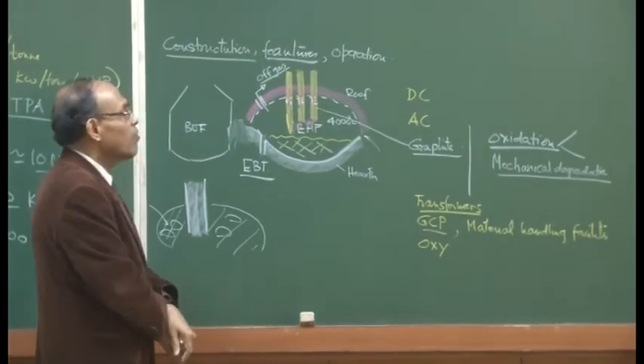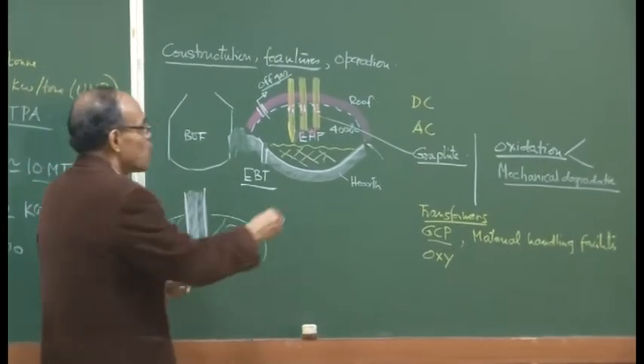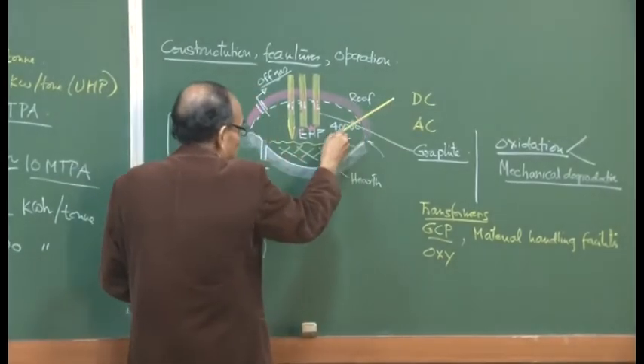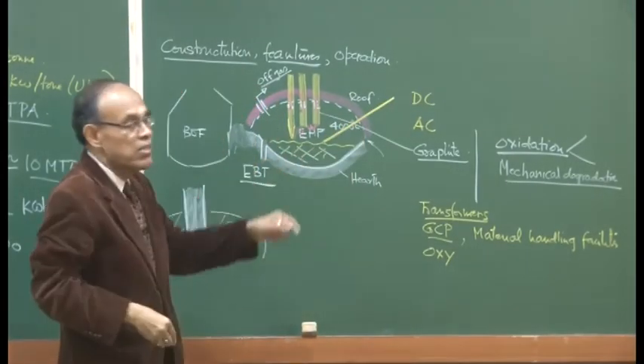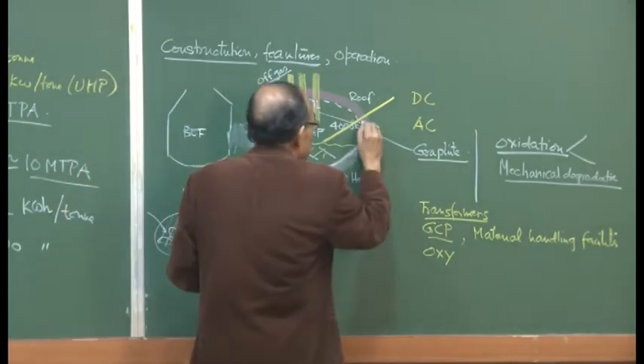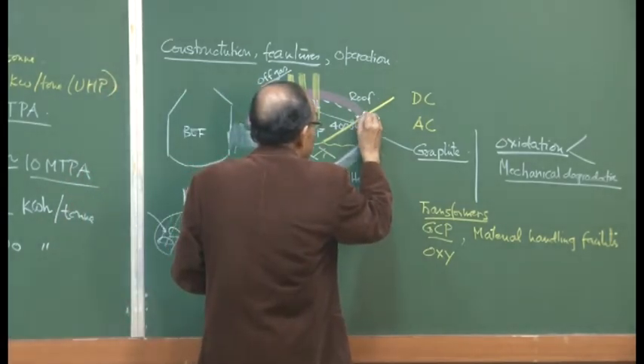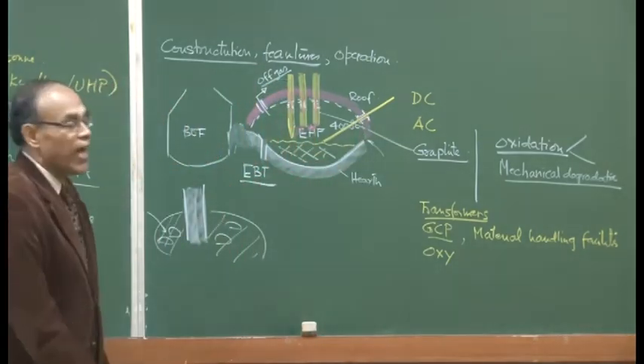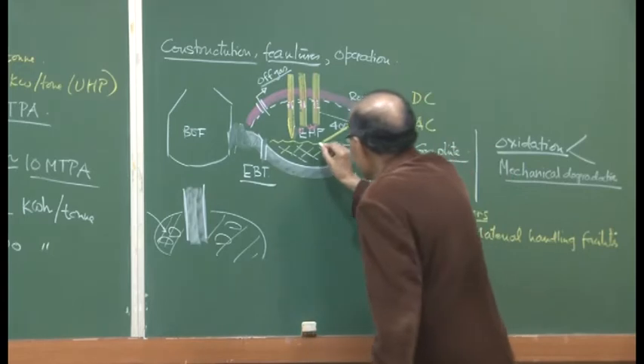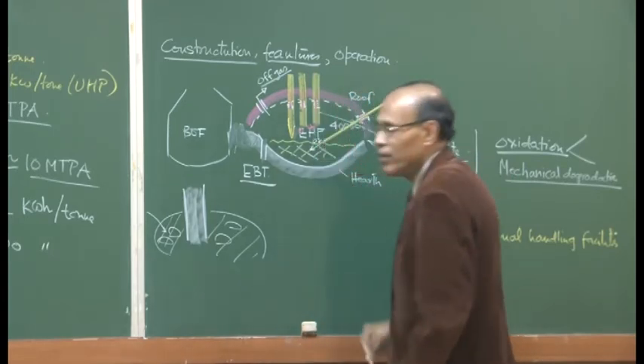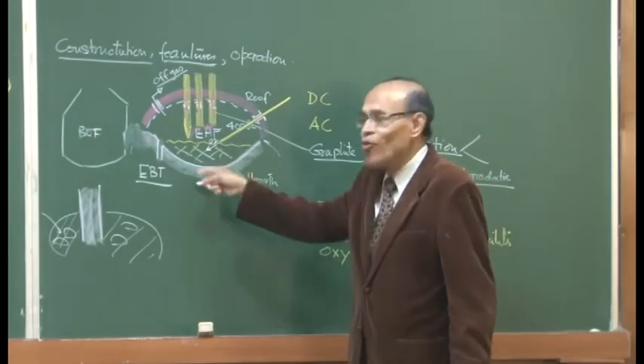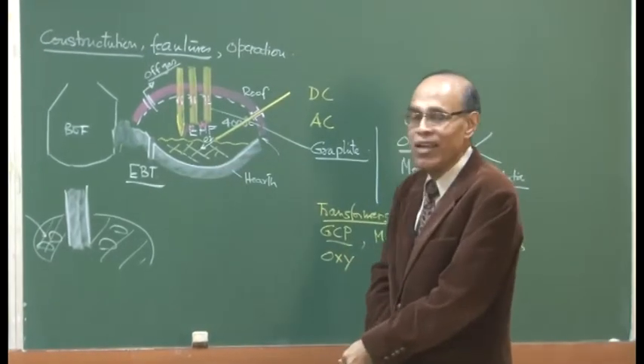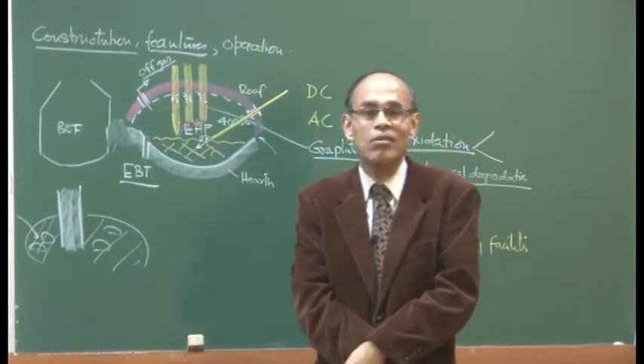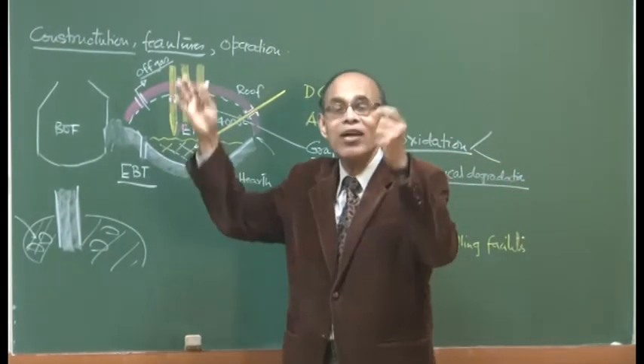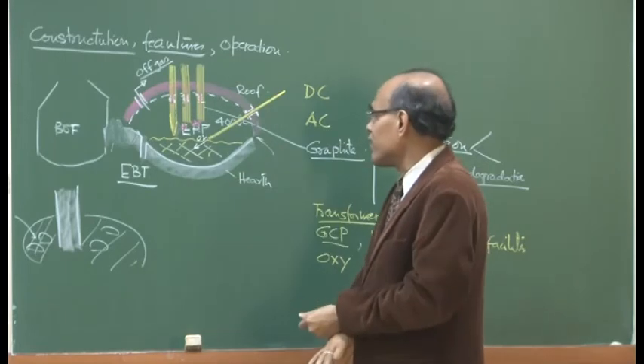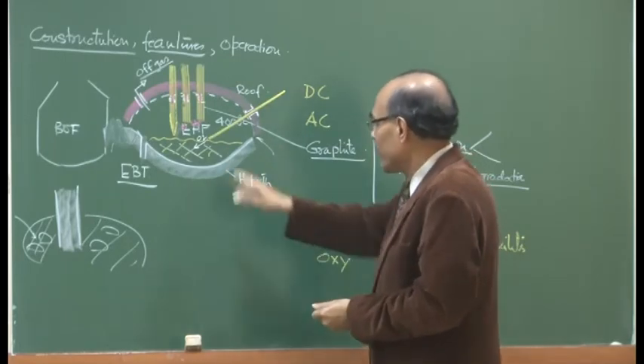So 40-50 years back, there used to be what is known as an oxygen lancing facility. So you have a lance, and that lance is a retractable, manually operated lance, and that lance is inserted, and through this lance the oxygen will be pumped into the system. In good olden days, iron ore used to be the oxidizing agent, but using iron ore will take the melting time anywhere between 8 to 10 hours if you want to process 50 or 100 tons of steel, hot metal, scrap in the furnace itself.